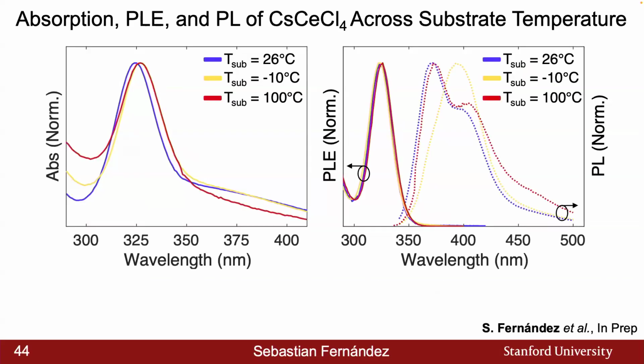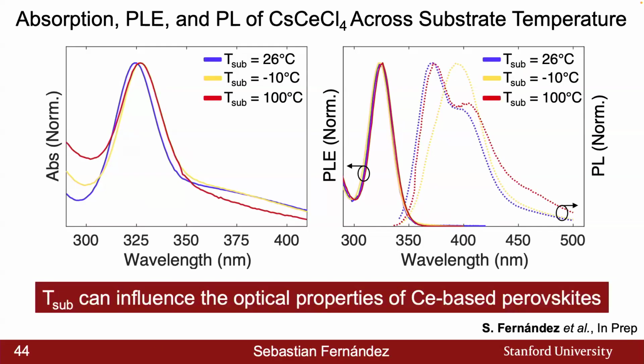And at the time, we're limited to 100 degrees Celsius. We've been able to move that slightly, but we can see that there's not too much of a difference between the 26 degrees Celsius and 100 degrees Celsius. But it's hypothesized that as we move further, perhaps we can further impact the photoluminescence spectrum of this material. But in general, showing that the substrate temperature can really influence the optical properties of the cerium-based perovskite.